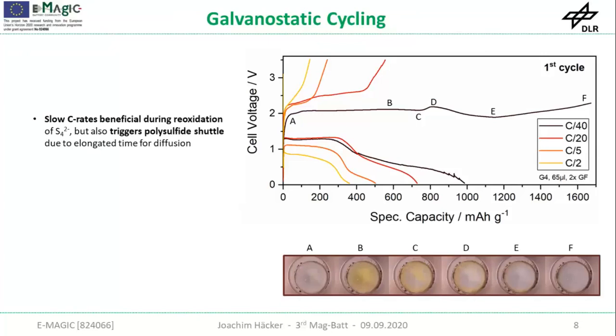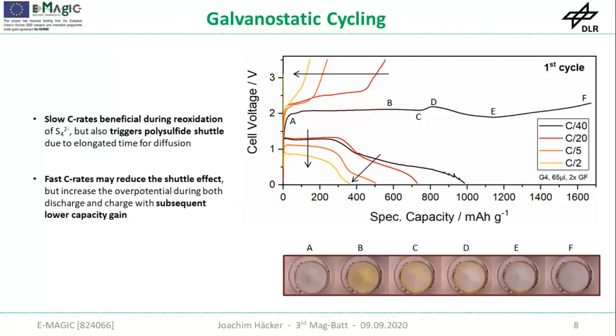So the polysulfides have elongated time for diffusion, which is not beneficial in the subsequent discharge. So you have detrimental effects on the anodes, which might not be too beneficial. Fast C rates, in contrast, increase the overpotential and also reduce the capacity gain. So you see here quite a significant influence.